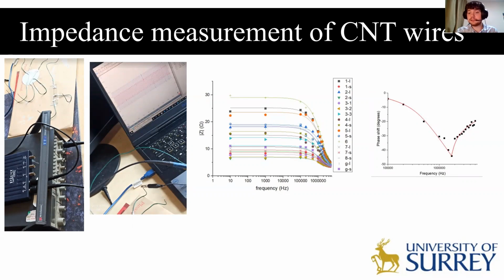I therefore decided to tailor most of my measurements to be around when the graph begins to tilt and where a peak can be observed, which can be seen in the first graph. In total, I have taken over 400 measurements, 23 per wire for 18 wires, which allowed me to get a very consistent pattern that can be seen.